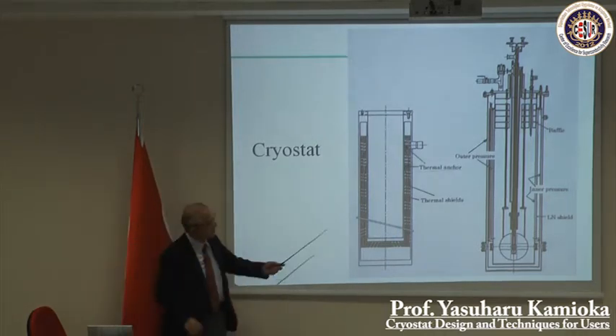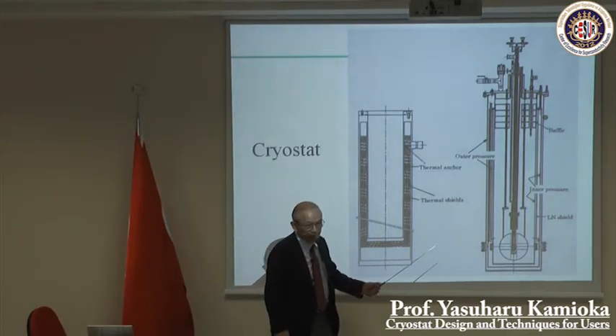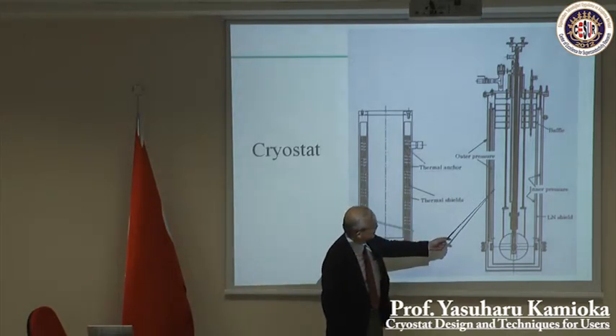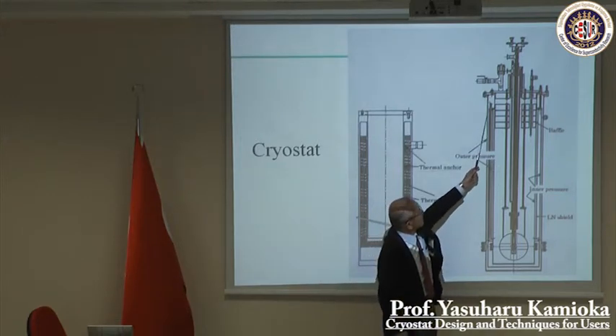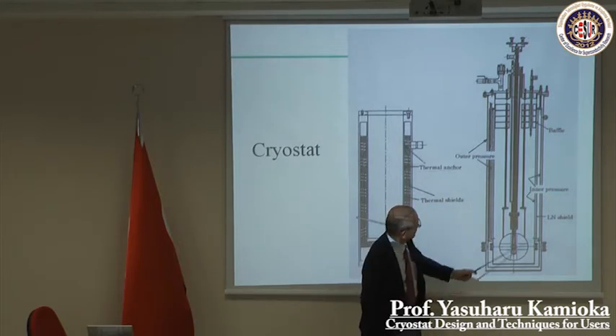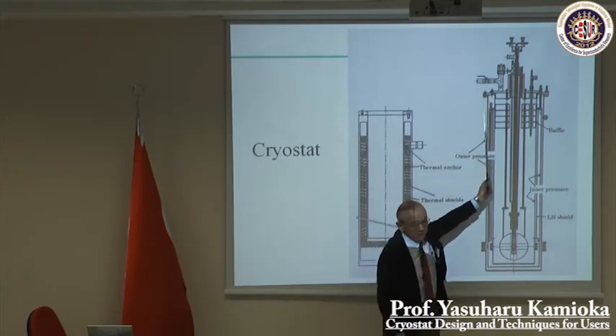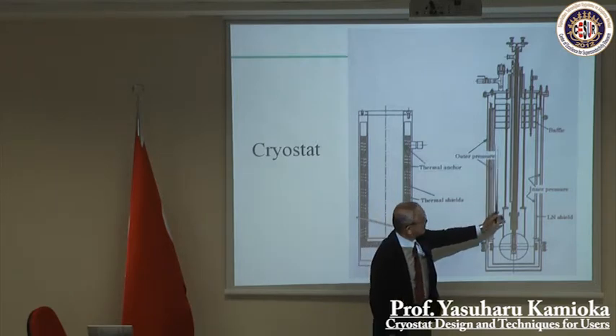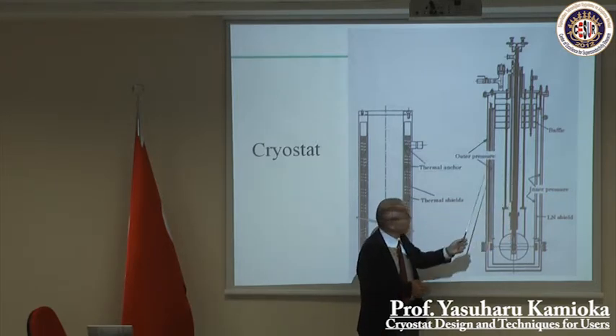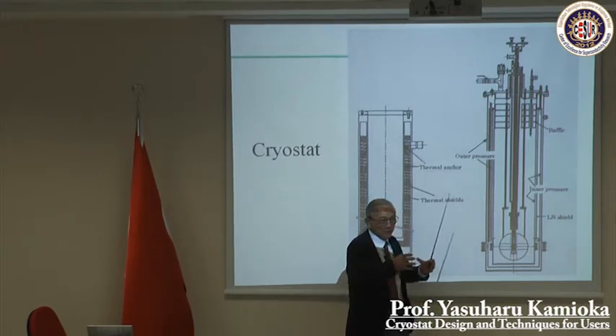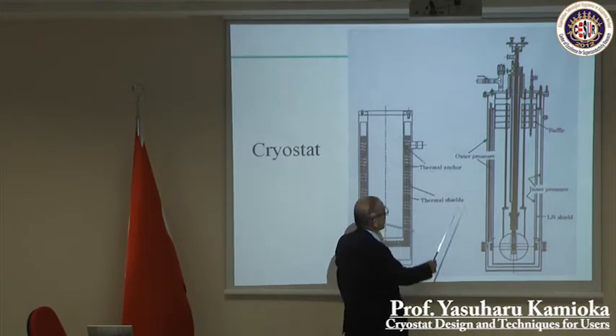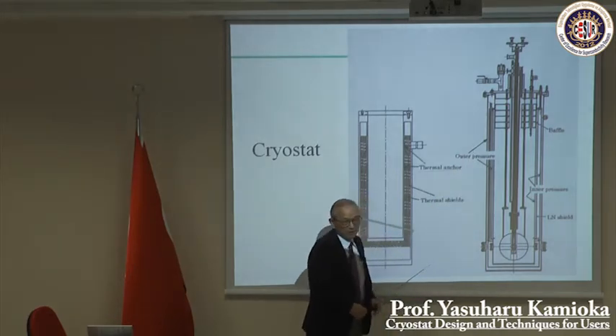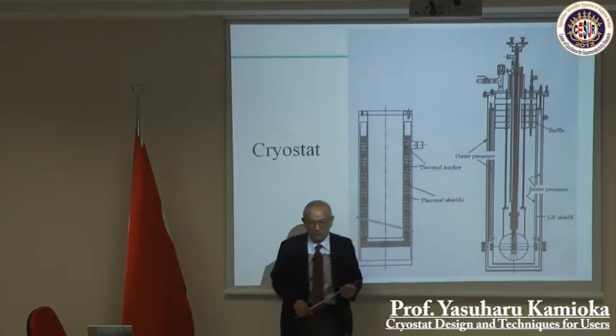And also when you have a helium leak test, before constructing the outside, you have to have a leak test only inside the chamber. But you cannot evacuate inside because of the very thin wall. It cracks. So we need the outside chamber also. Then make a helium leak test. Sometimes we have to have a chamber for the leak test.